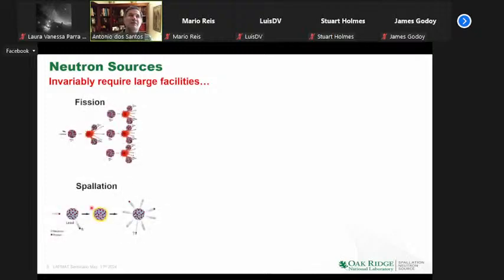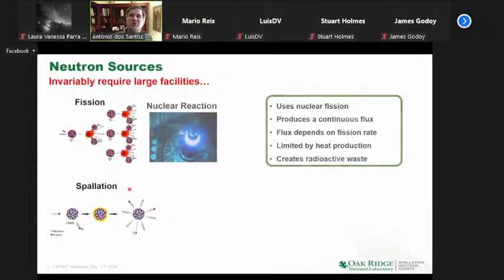And this is because it requires either fission or spallation. Now, starting with fission, which you are probably more familiar with, it requires a nuclear reactor. This is actually the image of the pressure vessel and a fuel replacement at our reactor at Oak Ridge called HFIR. So this uses nuclear fission. Basically, there's this cascading effect, and some of the neutrons come out. But the problem is that the flux depends on the fission rate and therefore is limited by heat production. You can't have a runaway process, and also the materials can't melt. The other problem, besides the obvious political one of creating nuclear reactors, is that it creates radioactive waste.